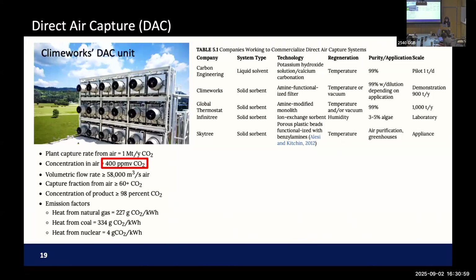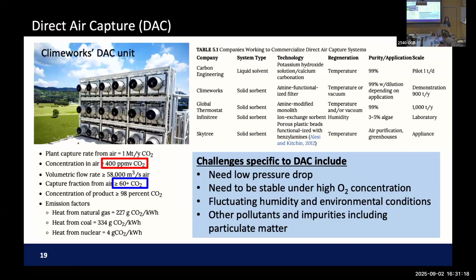The issue with this is that we are dealing with only 400 ppm, parts per million, of CO2, and because of that, there's no way we're going to go down to 95% plus CO2 capture. Generally, if you can scrub out more than 60% of CO2 from incoming air, you're good. That's the target. And there are other challenges. You need to process so much ambient air to get 1 ton of CO2. So if you have a high pressure drop in your system, you'll be paying so much energy for that. Whatever design you have, you should have a minimum pressure drop for sure.